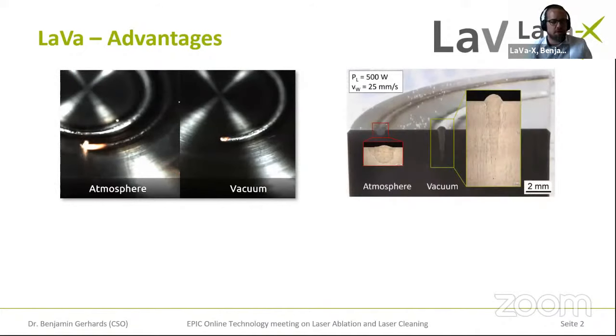If you look at the cross-section here on the right picture, you can see that when welding at atmosphere, we have quite a large molten pool. And when welding in vacuum, we can use the energy to go deeper into the material. So with just 500 watts of power in stainless steel, we can achieve a penetration depth of approximately 3 millimeters.